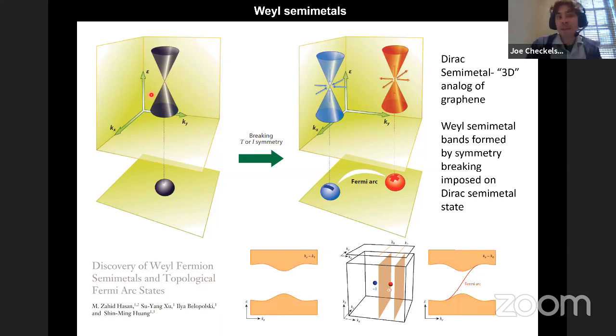And so you can make these a lot of different ways. One way to make them, as was originally proposed, is take basically a system where by some tuning parameter, you can go from a conventional insulator to a topological insulator. So through that transition, you close and open the band gap. And at that band touching point, you have a Dirac semimetal. So a variation on that is if you break a symmetry in these systems, time reversal or inversion symmetry, you split this Dirac cone into what we call 2 different Weyl cones.